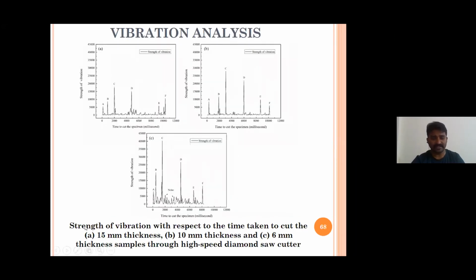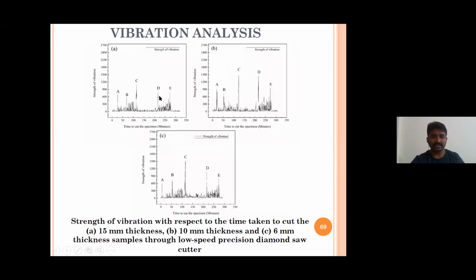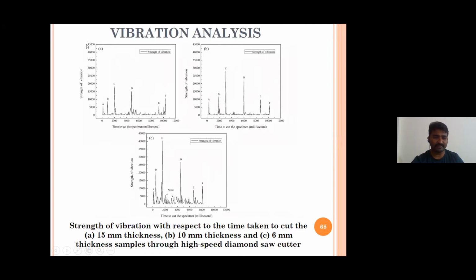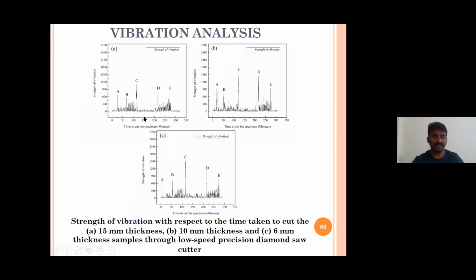This is for the high speed cutter, strength of vibration with respect to time taken to cut 15 mm with the high speed diamond saw cutter. As I told you, we have used 2 cutters for cutting the samples. One is a high speed diamond saw cutter, another one is a low speed diamond saw cutter. So this is the vibration study for the low speed precision diamond saw cutter. In the previous case, the values of strength of vibration varied up to 45,000. But for slow speed cutters, the maximum value it went to was nearly around 1500 or 1800.